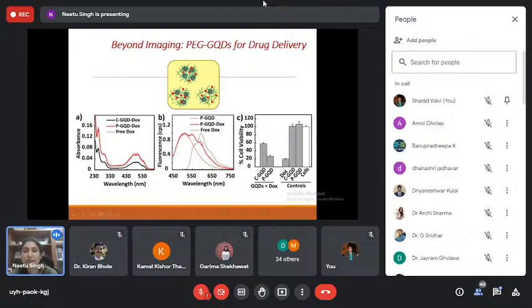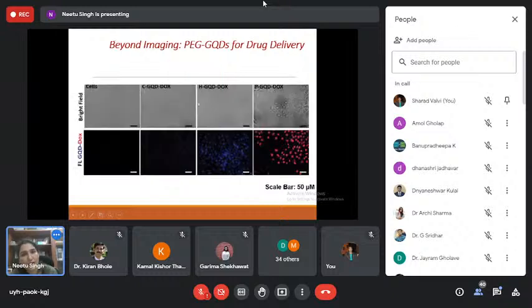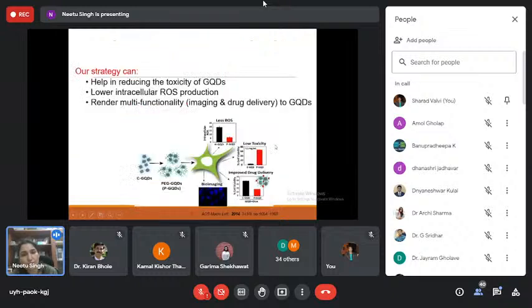Again, we started looking at, does it really reduce the toxicity? Can it actually deliver drugs? And we did all these experiments because now we have the gels, we can actually load it for drug delivery also. And that's exactly what we found. We were able to have beautiful nanoparticles which are coated with these polymers, and they were able to deliver drugs in them. They had less toxicity, and we were able to improve the toxicity. So the model system that we used for our study was graphene quantum dots, because graphene quantum dots have a lot of severe toxicity associated with them.